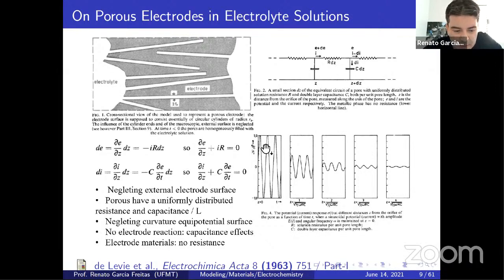So if you take a look here, for a short period of time and high frequency, we are studying the flat surface. However, for long times and low frequency, we have the porous surface. As we see here, the impedance, the voltage and the current as well, and the impedance divided by frequency. So as soon as we decrease the frequency, the impedance increases. So during the shorter time, we have the flat surface, and as we increase, like in this figure, we have a decrease of the amplitude of the signal, and now we are mapping the porous surface down there.